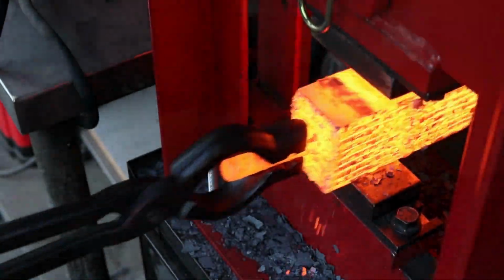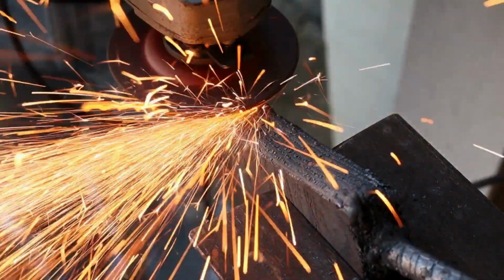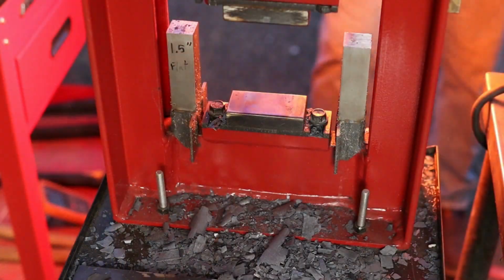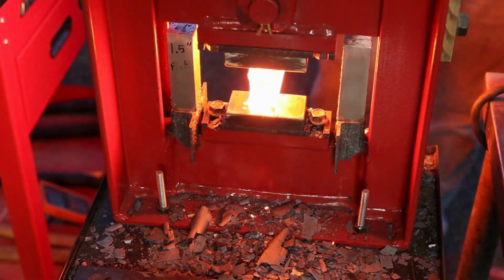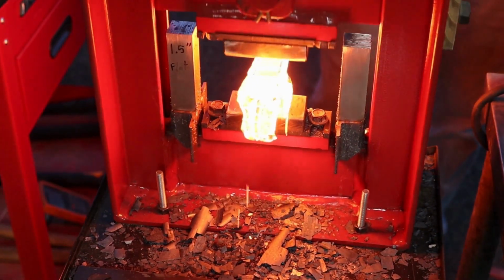After 3 or 4 heats, when I'm certain that the welds are fully set, I like to grind the edges of the billet and remove any tack welds. It seems like I end up removing a lot less material doing it this way rather than waiting until the billet's fully drawn out.